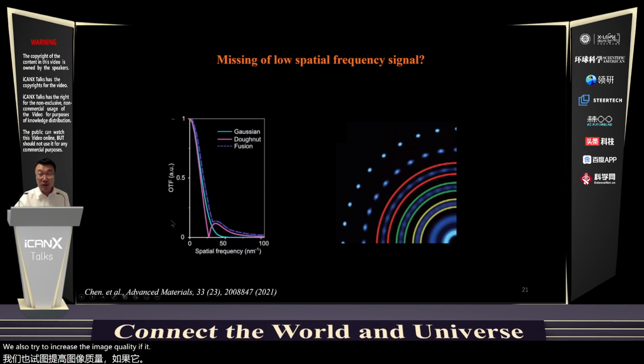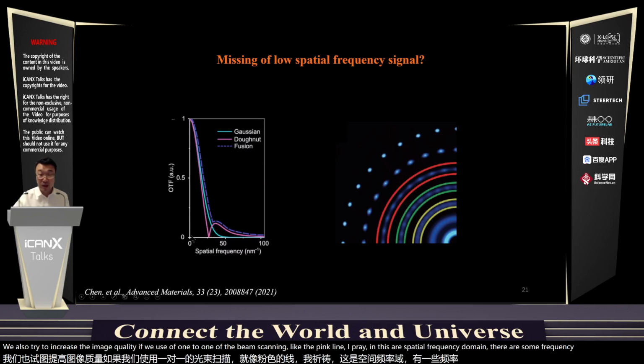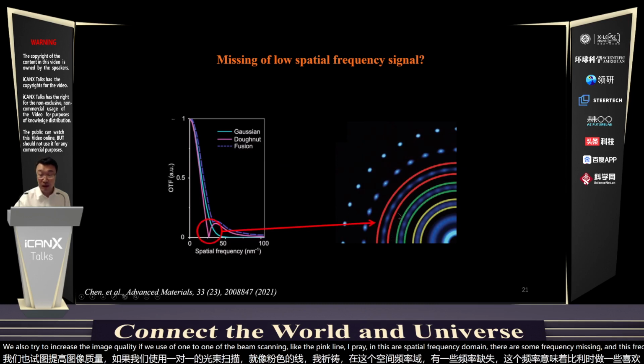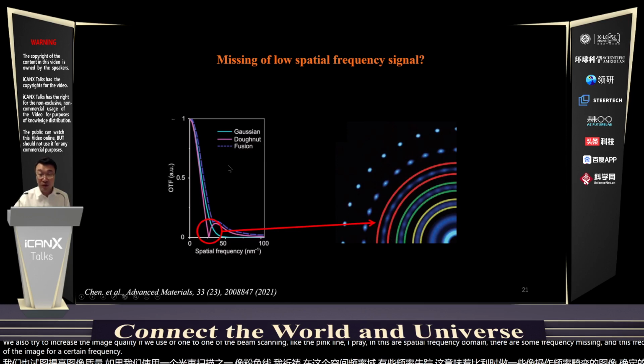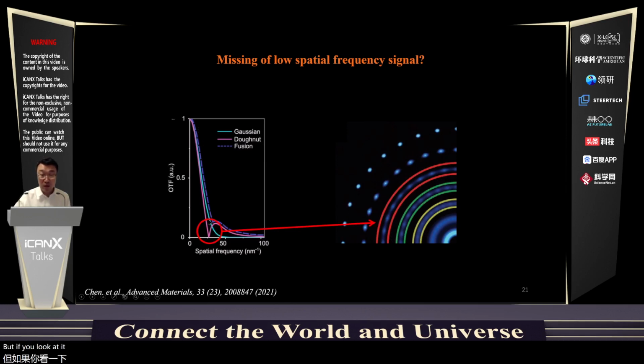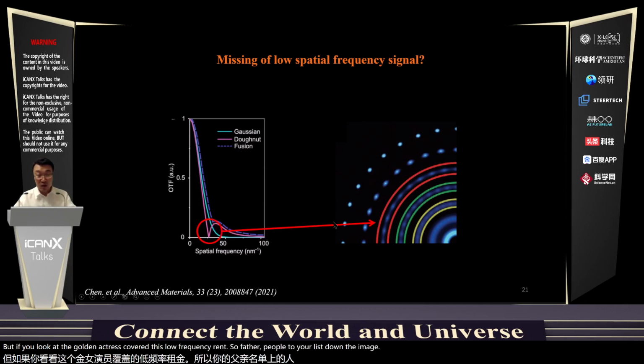If we use one donut beam scanning, like the pink line, in the spatial frequency domain there are some frequencies missing, and this will induce aberration or distortion of the image for certain frequencies. But if you look at the Gaussian, it covers this low frequency range. So other people usually scan the image twice and then do processing to solve the problem.